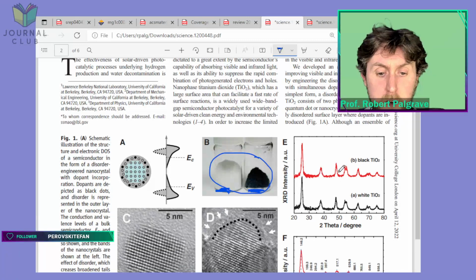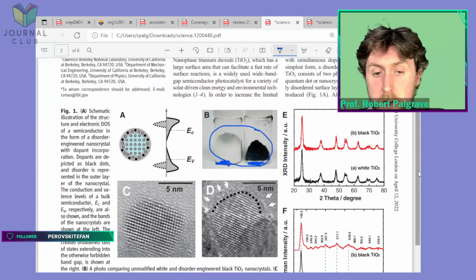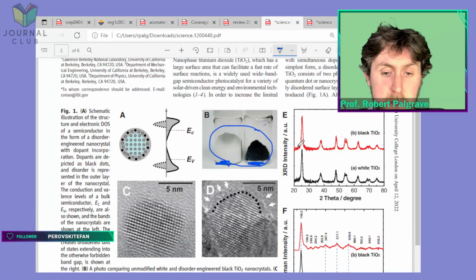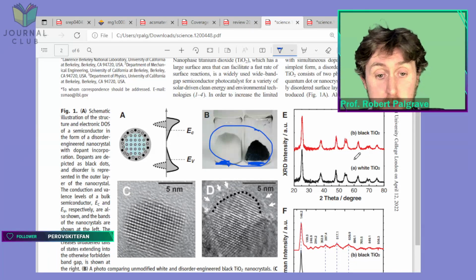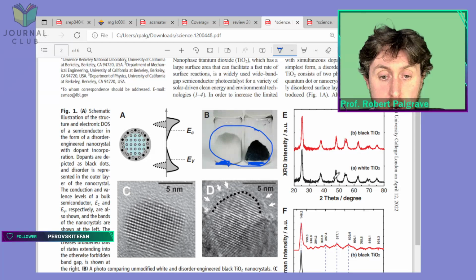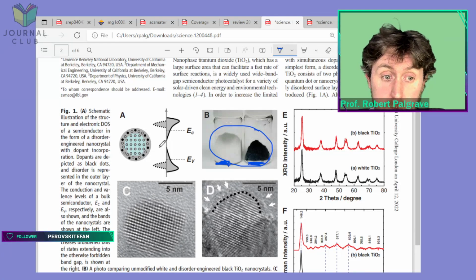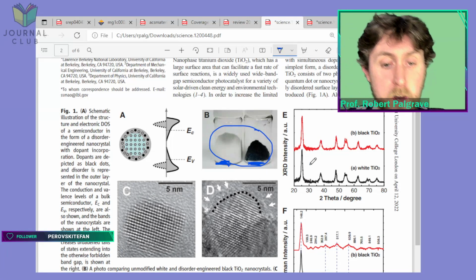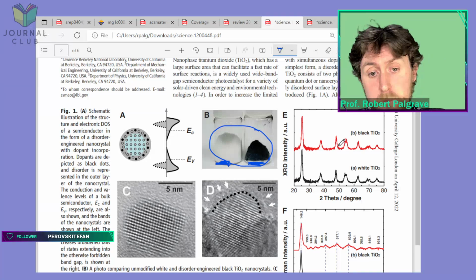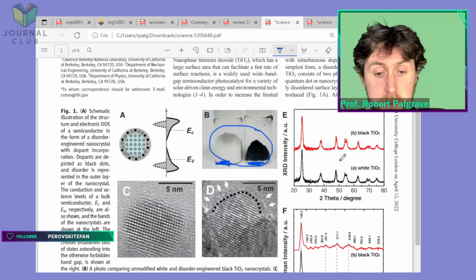But most of the characterization that they did of this material seemed to show that it was fundamentally the same material. So if they look at the X-ray diffraction here, which tells you about the crystal structure, it looks pretty much the same before and after. The peaks are very broad. That shows they've got nanoparticles, and that's indeed what they started with. Started with nanoparticles of TiO2, and still are nanoparticles afterwards. The peaks are pretty much as broad.